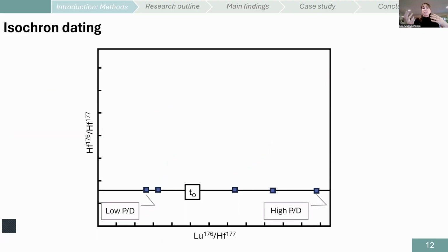An isochron is a line that's connecting the data points on the isotope composition diagram, where on the vertical axis, we have a ratio of our radiogenic hafnium-176 to a normal non-radiogenic hafnium-177. A similar ratio on the horizontal axis, we have lutetium-176, our radioactive isotope, to the hafnium-177, the same value of a normal hafnium that we have there. So if we start at time 0, which is marked as T0 right here, when the mineral assemblage forms. How it forms is a question for a different method, but we have our mineral assemblage forming at this particular time. At this point, all parts of the system are assumed to be in isotopic equilibrium.